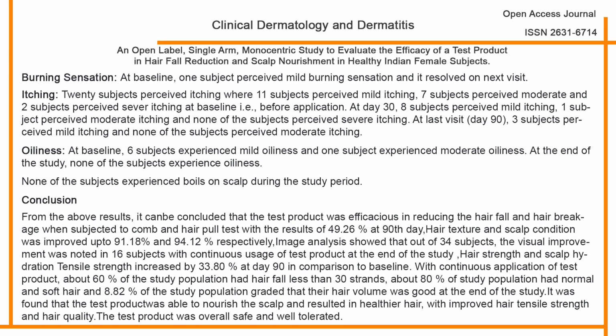Conclusion. From the above results, it can be concluded that the test product was efficacious in reducing the hair fall and hair breakage when subjected to comb and hair pull test, with the results of 49.26% at 90th day. Hair texture and scalp condition was improved up to 91.18% and 94.12% respectively. Image analysis showed that out of 34 subjects, the visual improvement was noted in 16 subjects with continuous usage of the test product at the end of the study.